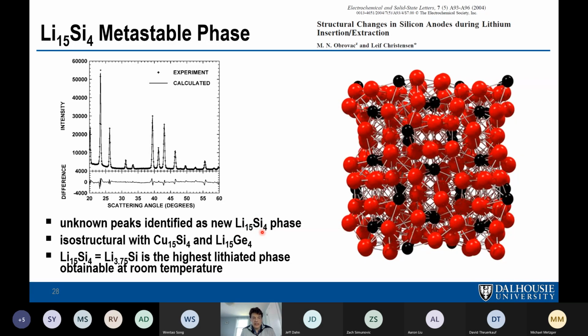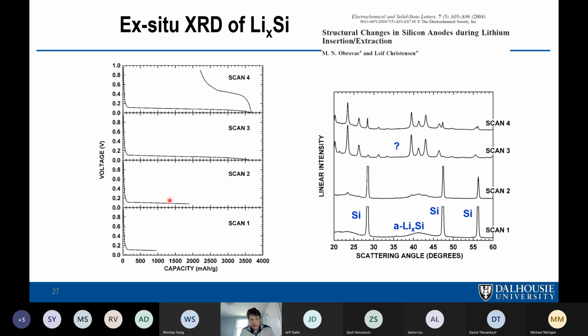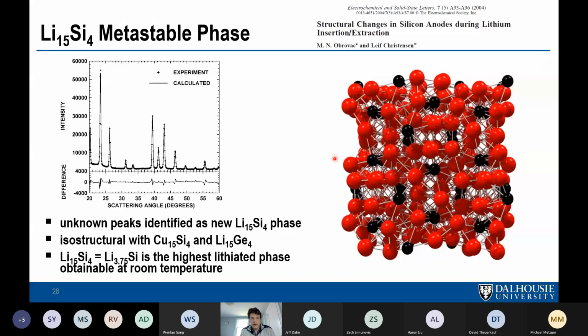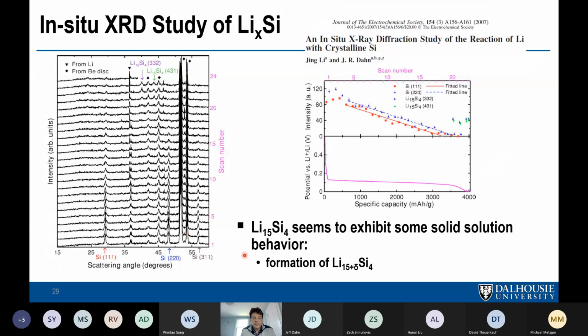The interesting thing too is how it's formed, because you could see it's not forming here, and then all of a sudden it pops out. And maybe we'll see that. Yeah, I think we'll see that better later on. Right here, actually. This is a later study from Jeff's lab doing an in situ experiment now. And you can lithiate the silicon in the two-phase region. So you have silicon peaks and they're going away. The intensity is going down as you're forming amorphous silicon. And then all of a sudden, when you get to about 50 millivolts, bang, you get this lithium 15 silicon 4 phase forming instantly, which is quite surprising.